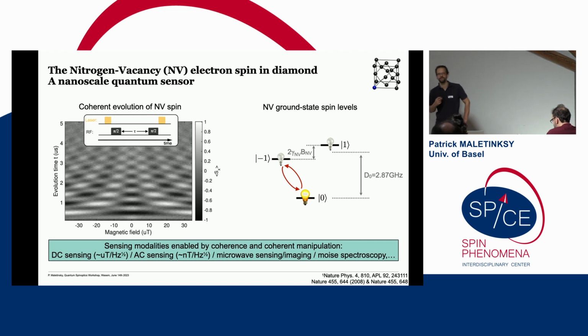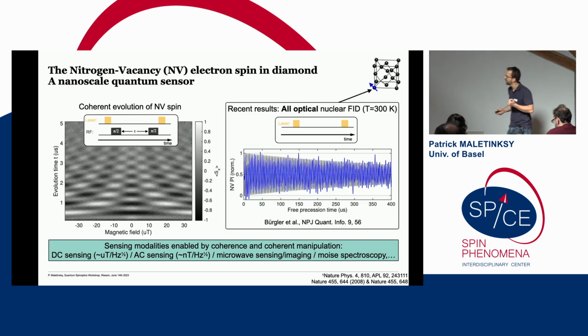But for certain applications, this may still be too much. If you're thinking about ideas that exist to miniaturize these sensors into compact packages, for instance, for geonavigation and other things, you want to minimize the number of control fields. And here I would just like to briefly flash a recent result we've had in my group that addresses this issue. This was in fact a chance finding that we had where we realized that if you tune this NV center to a certain regime of magnetic field, you can skip the radio frequency. What that means is that optical pumping, instead of initializing the spin into an eigenstate, it can initialize the spin also in a coherent superposition state. And I should stress this applies to the nuclear spin here attached to nitrogen of the NV center.